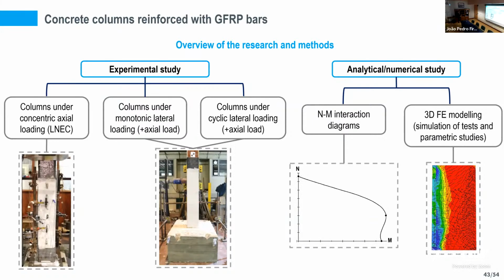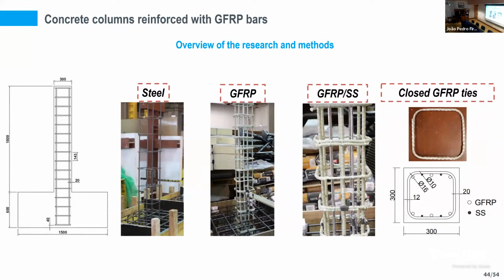For that, we designed an experimental study combined with a numerical study, where we tested real scale concrete columns reinforced with GFRP bars, subjected to axial loading, tests that we performed at LNEC, and concrete columns and the corresponding footing system that we tested under constant axial load and subjected to monotonic lateral loading or to cyclic lateral load. Some examples of the rebar configurations that we adopted. Of course, we also tested reference steel reinforced concrete columns, and all-FRP concrete columns with longitudinal GFRP bars and also with closed GFRP ties that were specially manufactured by the FRP producer.